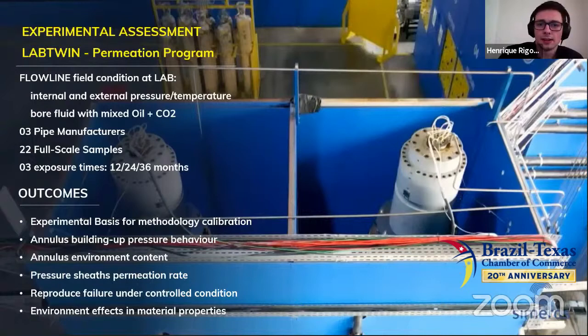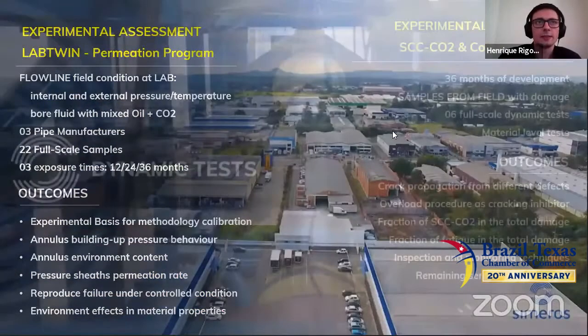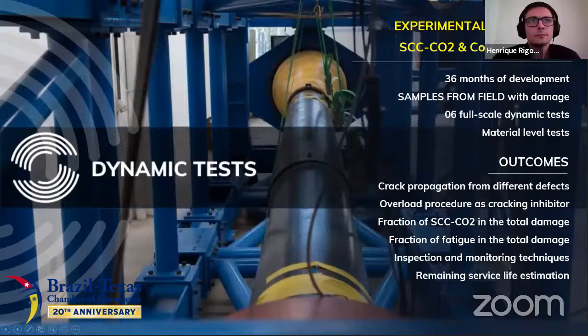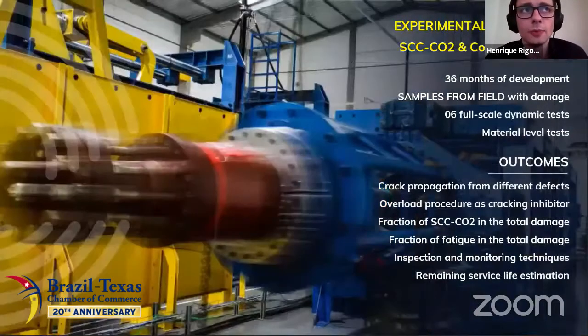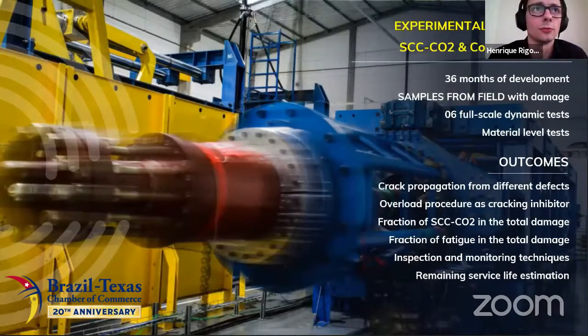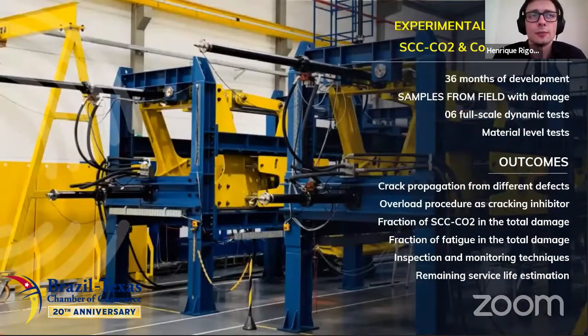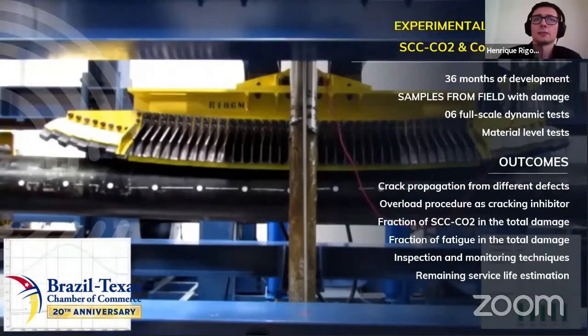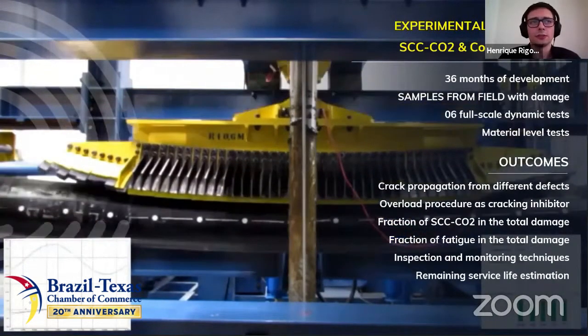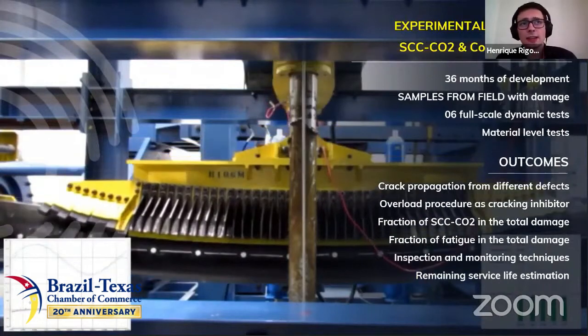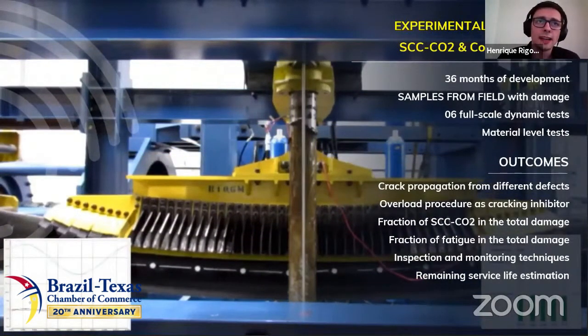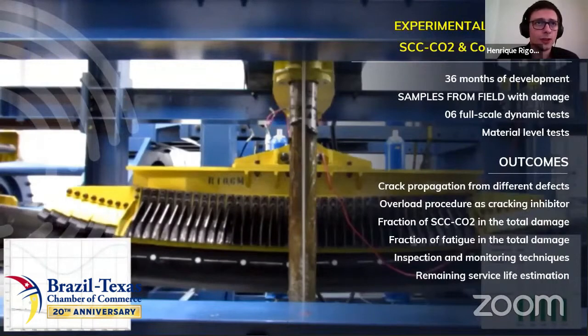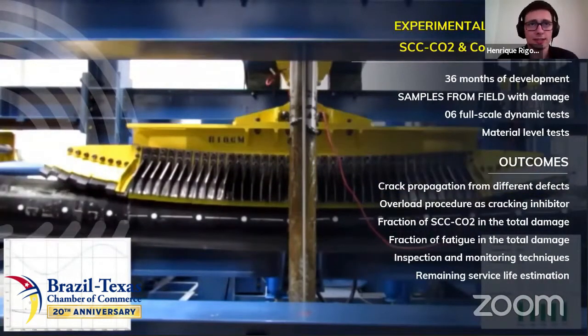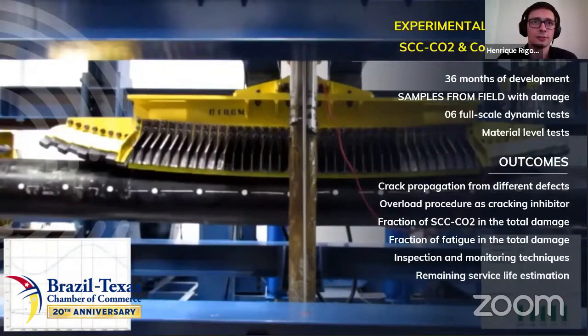Hello, everyone. So following the mentioned initiatives in experimental assessment, SIMEROS is investigating the relationship between SCC CO2 and dynamic loads. SCC damage can be exacerbated by other failure mechanisms, which represents one of the major concerns in the industry. The main concern is that SCC CO2 can quickly initiate damage, which, combined with dynamic loads, may speed up the damage propagation up to the catastrophic failure of the structural armor layers.